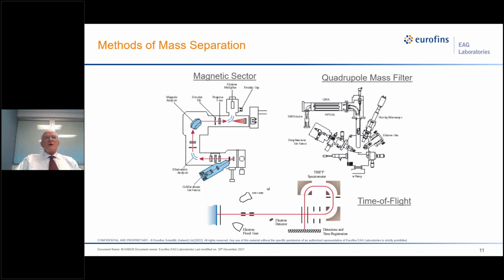There are three different types of mass separation. We have the magnetic sector instrument over here, the quadrupole mass filter, and the time of flight. Common to all of them is a primary gun here to bombard the sample. And the ions are extracted from the sample here in this magnetic system. They're energy analyzed, and this magnet really separates the ions according to their mass to charge ratio, and then the ions are detected. Same with the quadrupole, except the ions are extracted this way, energy analyzed, and now instead of a large magnet, we do the mass separation with a quadrupole mass analyzer.